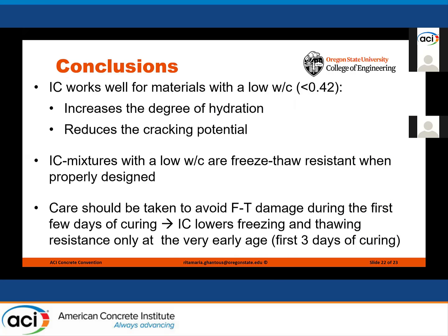To conclude, internal curing works well for materials with a low water to cement ratio by first increasing the degree of hydration, reducing the cracking potential, and when properly designed, internal curing mixtures with a low water to cement ratio will be freeze-thaw resistant. And then care should be taken to avoid freeze-thaw damage during the first few days of curing, which means that internal curing lowers freezing and thawing resistance only at very early ages, the first 3 days of curing. So that's all. These are for low water to cement ratio.